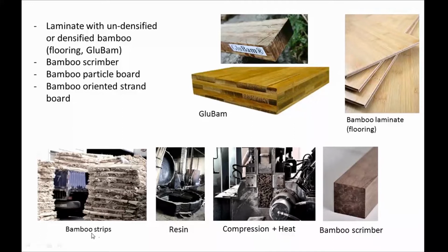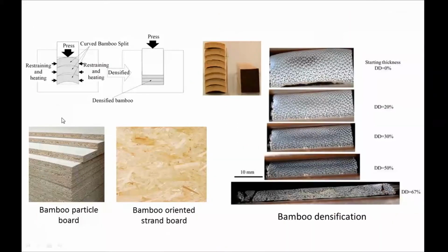For example, you can make a bamboo scrimber. You can make bamboo strips with resin inside, and with compression and heat together, you can make the bamboo scrimber. And you can put some pieces of bamboo together, and with pressure and heat, densify them. It's a densification process you can see. Starting the densification, you have 20% densification, 30%, 50%, and finally 67%. As you remember, we have much porosity in the bamboo, and you can compress all of the porosity. You can see bamboo particle board and bamboo oriented strand board here. Also 2 other products made from bamboo.